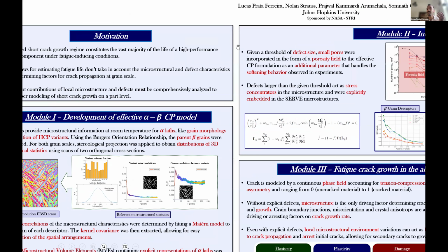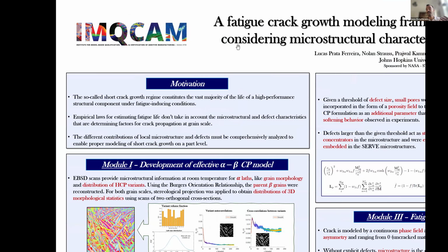In components and structural parts that demand high performance and are subject to fatigue loading and fail by fatigue loading, we know that about 80% of the part life is encompassed within the regime of short crack growth and crack nucleation. The long crack growth takes only the remaining time of the part life.